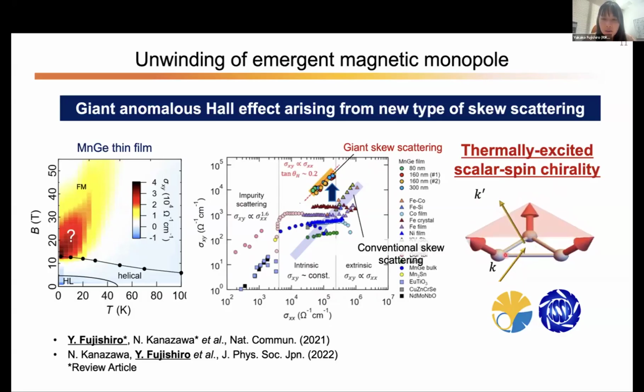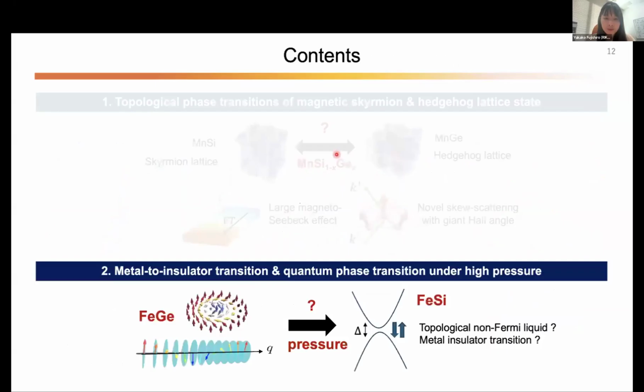And actually, this model reproduces the giant skew scattering Hall angle of about 20%. So we speculate that this kind of remaining residual scalar spin chirality, which is thermally excited, is actually present in this high field region and produces this unusual giant skew scattering in this compound.